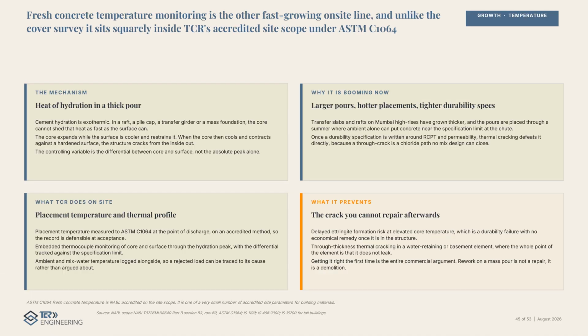Fresh concrete temperature monitoring is the other fast-growing on-site line, and unlike the cover survey, it sits squarely inside our accredited site scope under ASTM-C 1064. Cement hydration is exothermic. In a raft, a pile cap, or a transfer girder, the core cannot shed heat as fast as the surface, so the core expands against a cooler restraint, then contracts against a hardened surface, and the element cracks from the inside out. The controlling variable is the core to surface differential, not the peak alone. We measure placement temperature on the accredited method and track the profile through the hydration peak.